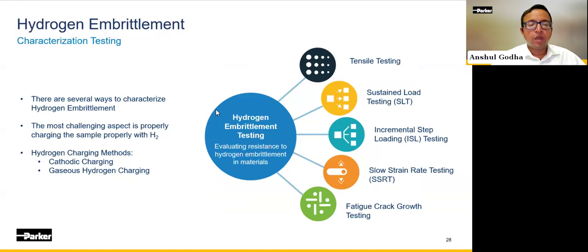So how do we test for hydrogen embrittlement? The way we think about it is there are two individual buckets that we can categorize the testing in. The first bucket deals with how we charge the alloy with the hydrogen. The second bucket deals with applying mechanical load to see the effect of the hydrogen embrittlement that has occurred in the metal. In terms of the charging, again, there are two subcategories. One of them is where we first charge the alloy chemically with hydrogen and then apply the mechanical load, or we can just introduce gaseous hydrogen at pressure to the alloy and get our charging that way.